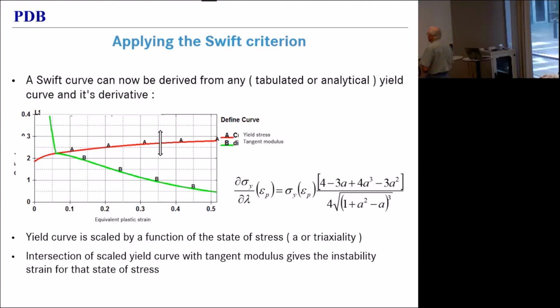If you now want to know the start of localization for any other state of stress, you compute the value of A. That gives you a multiplication factor for the red curve. You move your red curve up or down by that multiplication factor, and you look for the intersection point with the green curve, which you don't touch. And that gives you the value of equivalent plastic strain, where localization starts for that particular state of stress. So you can very easily implement that with Excel, which is, I think, what you did, Marin? Yeah.